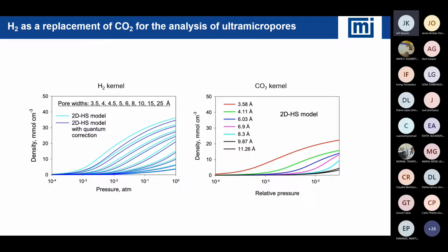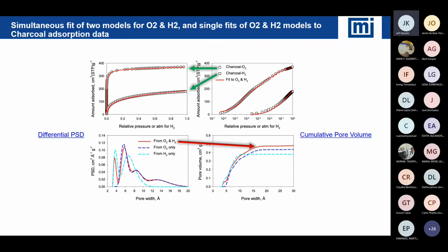So you notice on the right side for CO2, you only see a single isotherm for every size, right? So in red, 3.58 angstroms. But on the left side, when you look at hydrogen, notice there are two for each size. There's a light blue and a dark blue for each size. The light blue is if you assume hydrogen is just a hard sphere. The dark blue is if you take into effect that at 77 Kelvin, hydrogen wobbles a little bit. It has a quantum effect. So hydrogen is effectively slightly larger than we would consider if we just modeled it as a hard sphere. So it's an extra correction we have to consider.